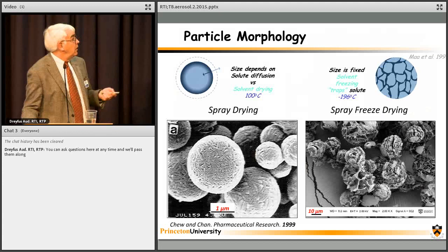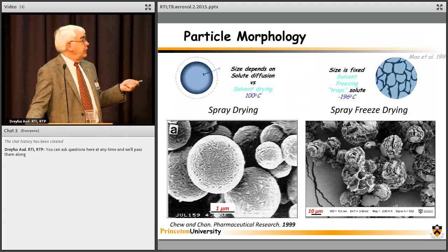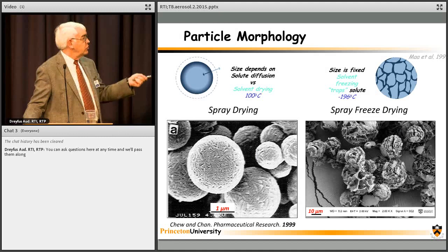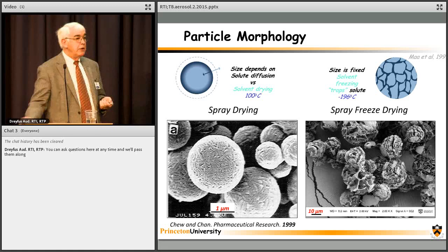So this is contrasting normal spray drying with mannitol, where these dilute solutions, as they dry, the thing gets smaller and smaller and more dense until you get to this structure here. In this spray freeze drying, we can make these porous particles where we can change the density of the particle by the amount of solids in the initial spray.